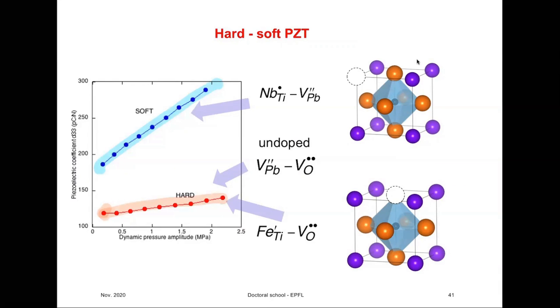Now, I didn't tell you, but the difference between these two compositions is just that one of them has 1% of niobium and the other one has 1% of iron. I think that's the amount. It's the same composition otherwise. The zirconium to titanium ratio is the same. So it's not that they are coming from two different regions of a phase diagram. Same chemical composition, just about 1% of dopant. Now let's see what these dopants are doing.